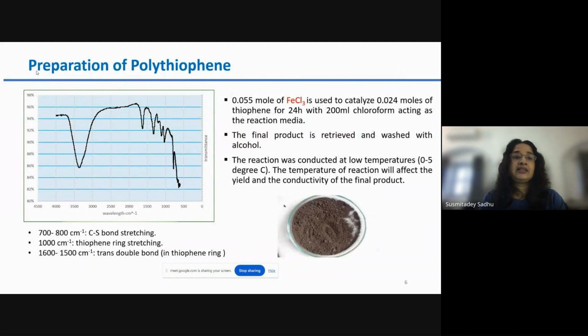And as I said, we have used polythiophene as the heterogeneous phase. So here we have synthesized the polythiophene in the lab using FeCl3 as the catalyst in chloroform medium for 24 hours in 200 ml chloroform, and the temperature of the synthesis was kept between 0 to 5 degrees centigrade.